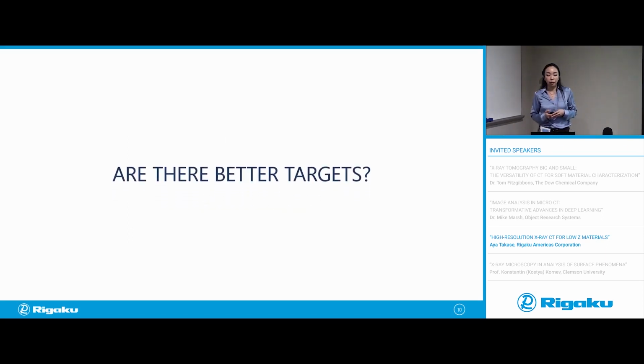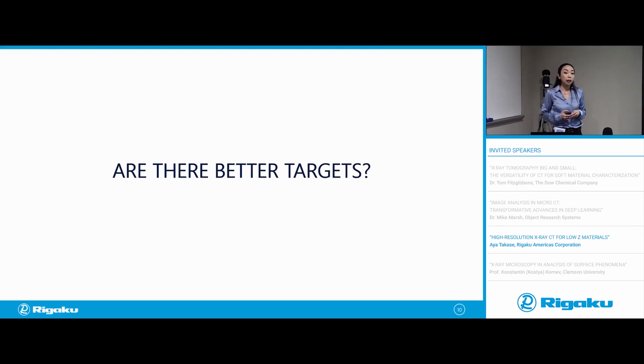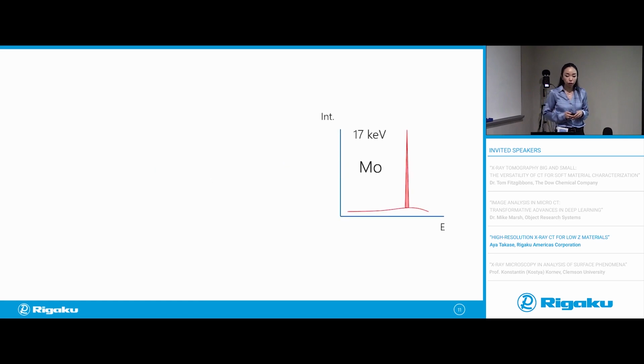So if tungsten is not the best target, are there any better target materials? There are a couple of different things you can use. Molybdenum is one of them. If you use molybdenum as your X-ray target, instead of a broad spectrum, you can have a really sharp peak at 17 keV. That is called the characteristic radiation because that 17 keV energy is characteristic to the molybdenum material. There is a little bit of broad spectrum at the bottom when you use molybdenum. That's this part. But the main X-ray photons you're getting from a molybdenum target is the 17 keV energy. It's a really narrow bandwidth and high intensity, so it's a really convenient radiation you can use for low energy imaging.